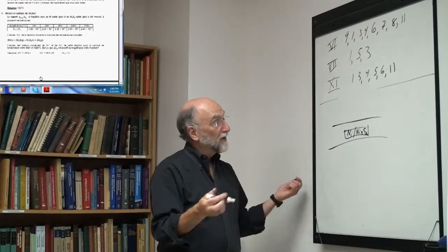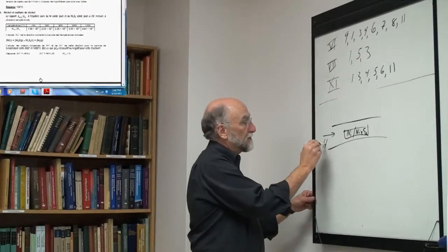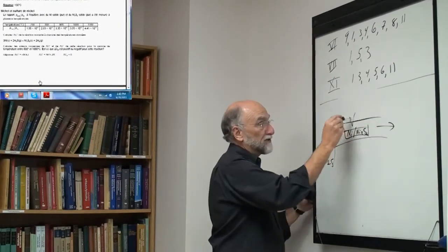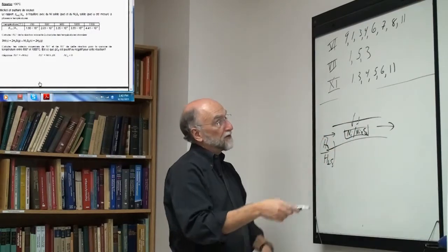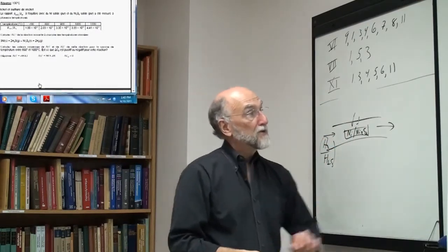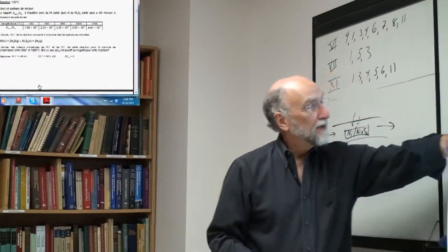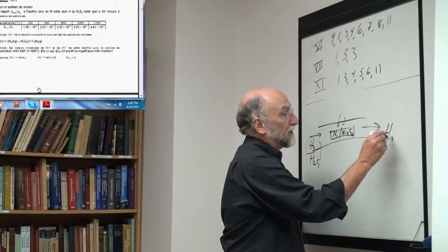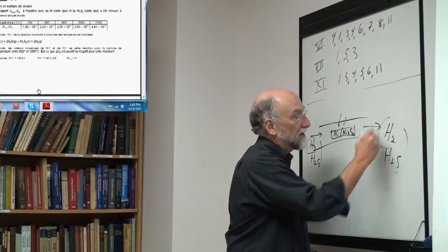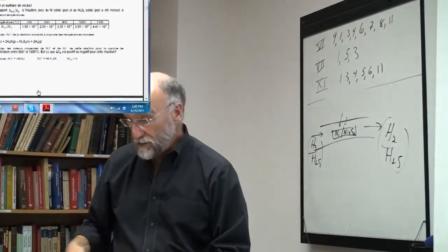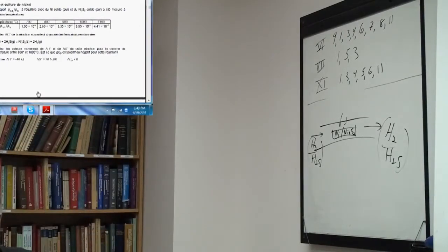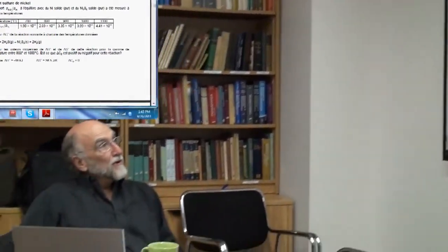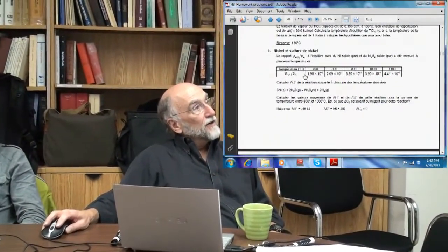So it's powder, so you have a large surface area. Here you pass a mixture of H2 and H2S, and you assume that there's an equilibrium. The gas passes very slowly, and equilibrium is reached between the gas phase and the solid phases, and then you measure the H2 and H2S pressures at the exit, and you assume that's the equilibrium pressure. Okay, so you measure that, and then for this reaction, delta G0. So these are your equilibrium pressures at various temperatures.